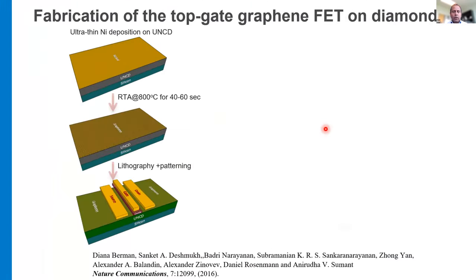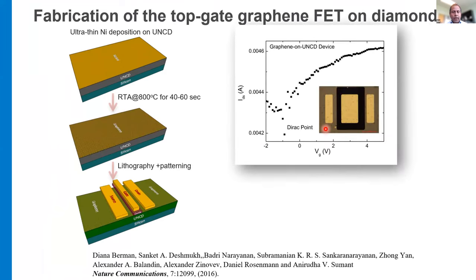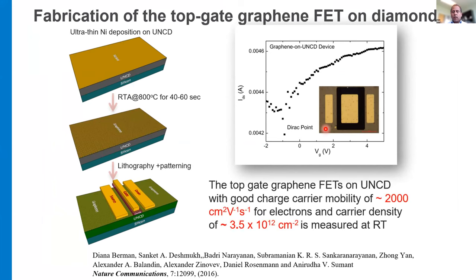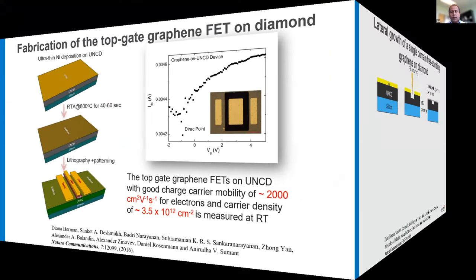And then another way to check the quality, of course, is to make a device through this patterning process and then look at the carrier mobility. And we got a very reasonable mobility for electrons, as well as carrier density, at room temperature. So this is very good for RF transistor applications. And then you can really pump very high current density through these graphene layers.